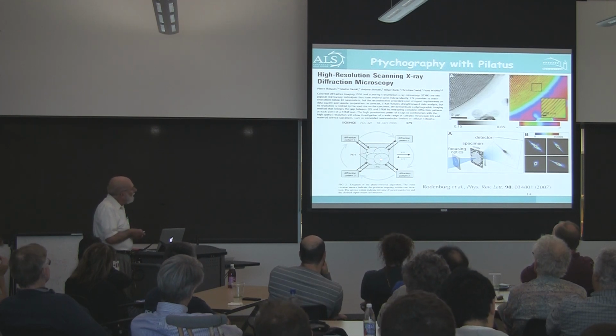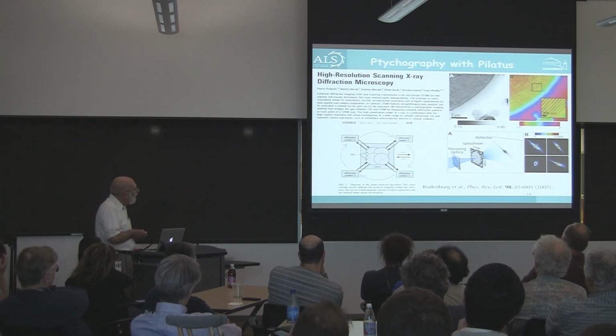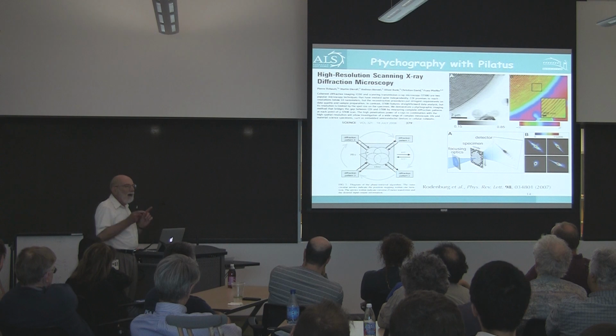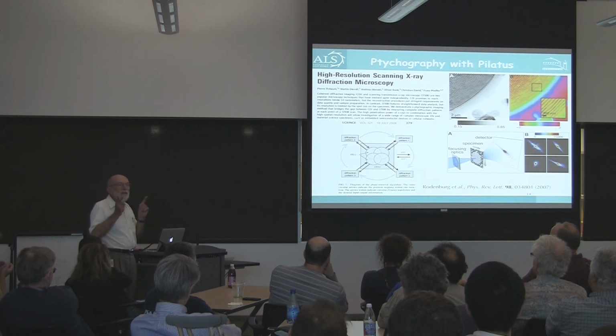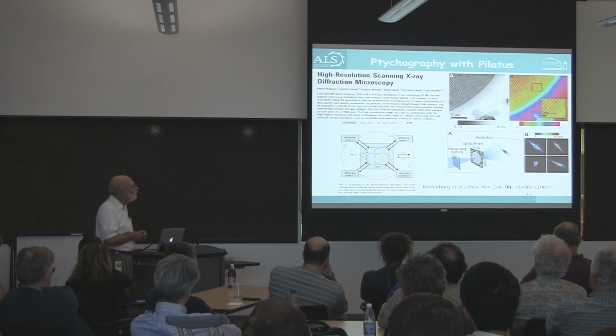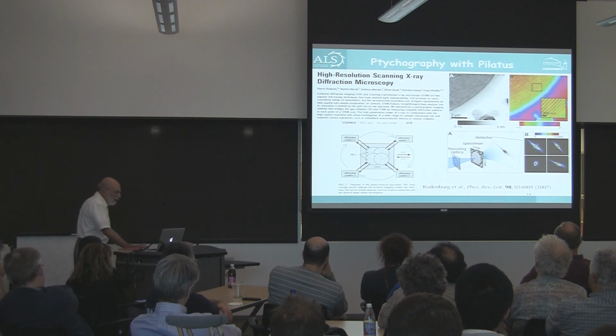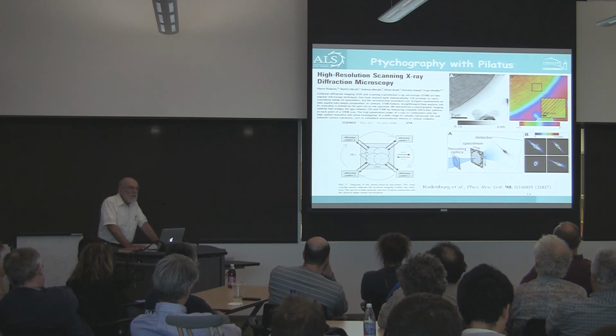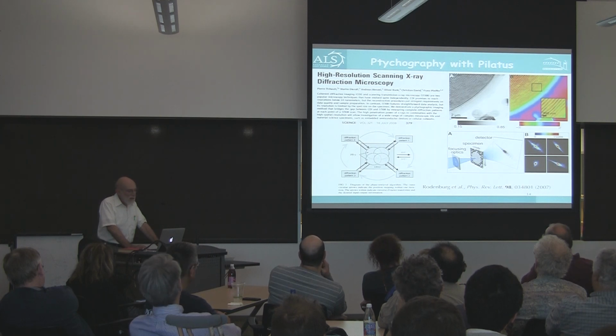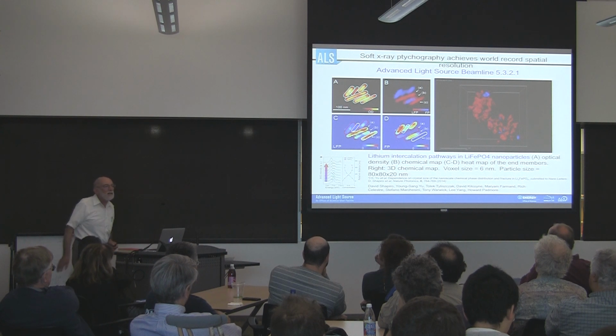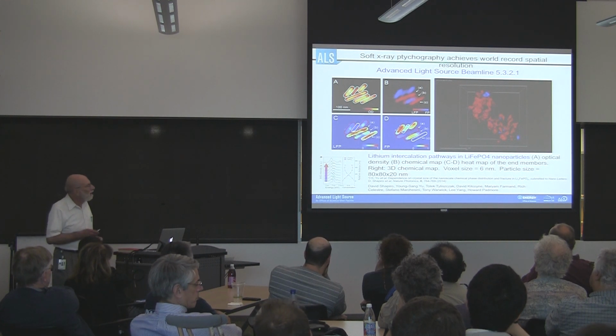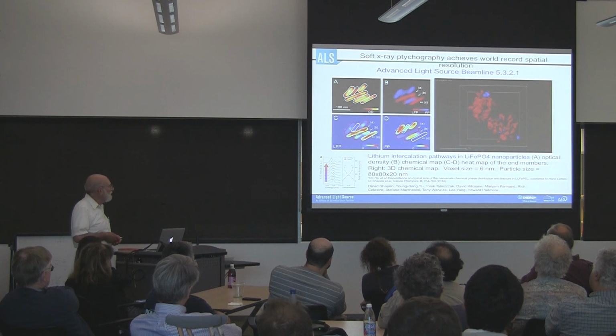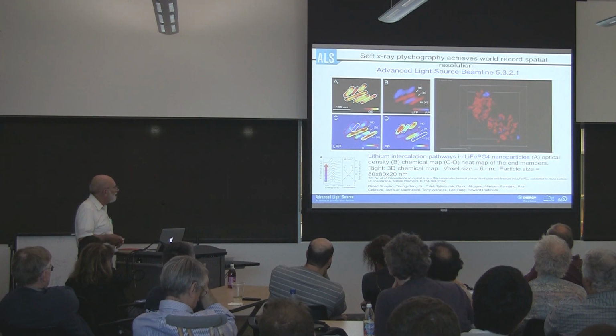What you do is you take diffraction patterns from overlapping spots on the specimen. And it is this overlap that gives you the information that makes it possible to do the reconstruction. And they beautifully demonstrated this, and this is a much more rugged form of diffraction-based imaging, and it has taken off like wildfire and is being pursued in a variety of places, but nowhere better than it is done at the ALS. And so what I'm showing you is material that I got from David Shapiro a couple of days ago.